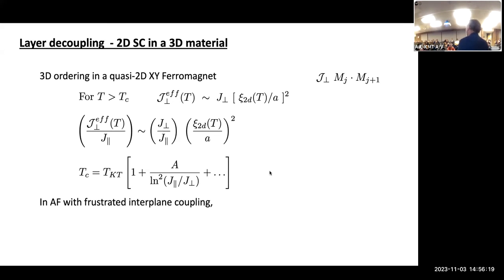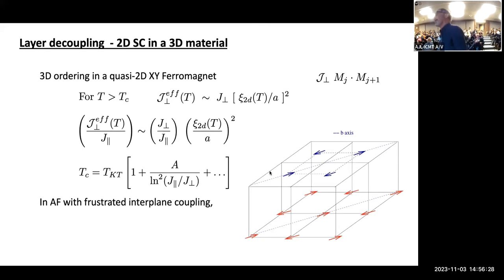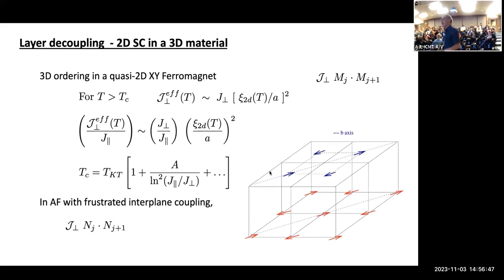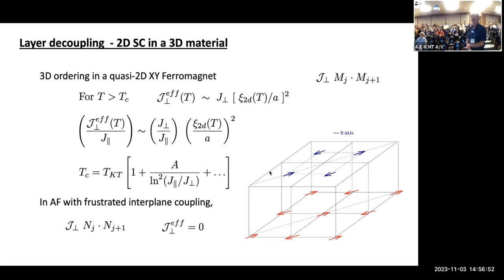Now, this is better for an antiferromagnet. You can imagine having antiferromagnets where the interplane coupling is frustrated. So here's a picture. This actually turns out to be a picture of what undoped lanthanum cuprate looks like, where you have an antiferromagnet in one plane. The antiferromagnet in the next plane has its sites above the plaquette centers of the plane below, so that the coupling of the Néel order in neighboring planes is 0.